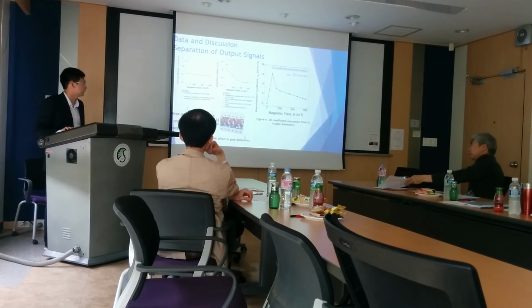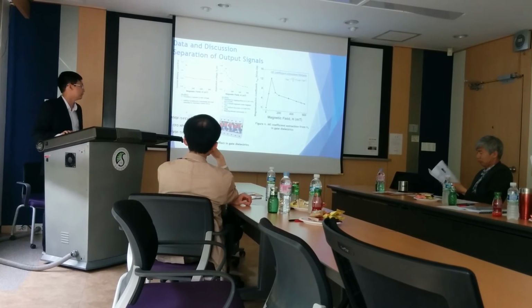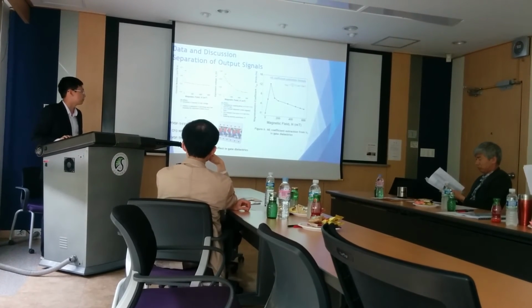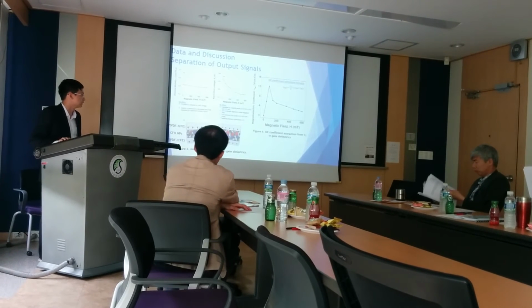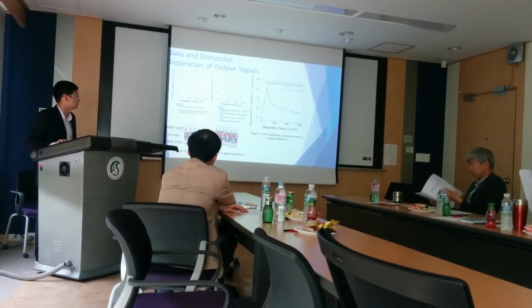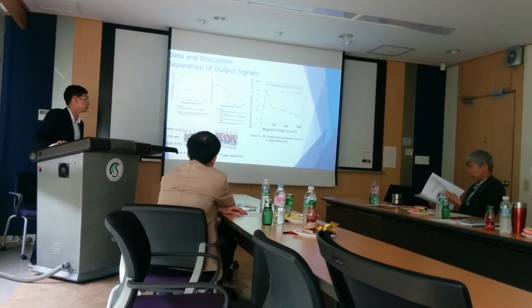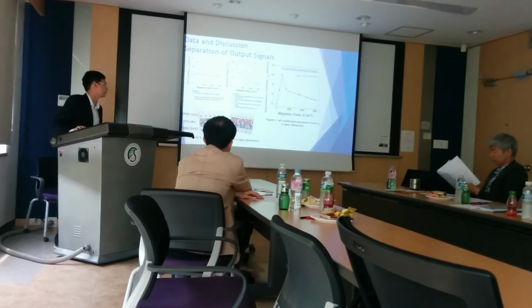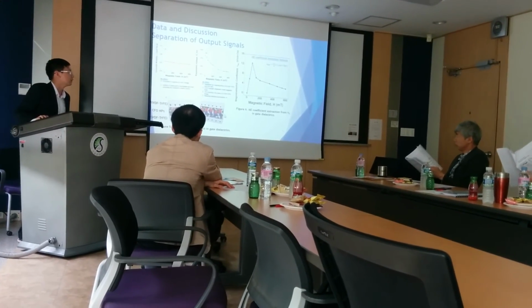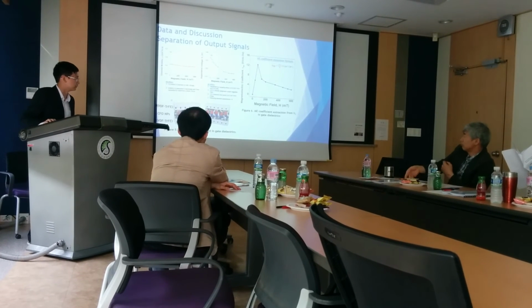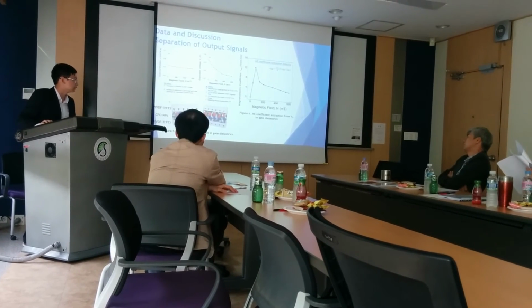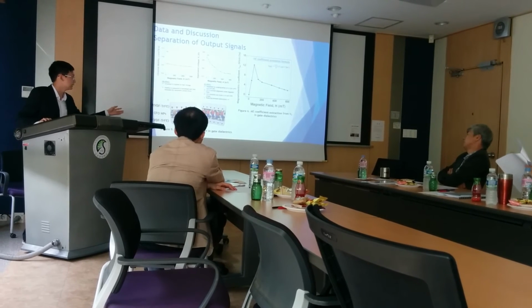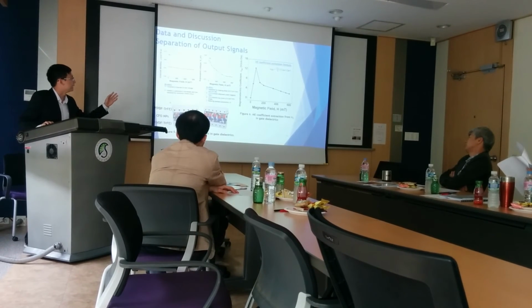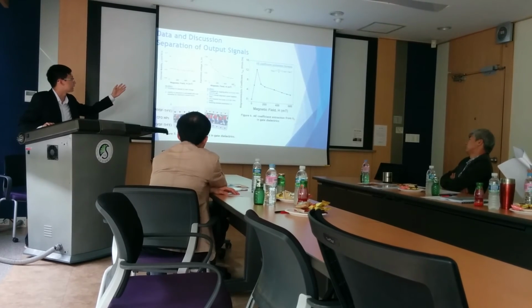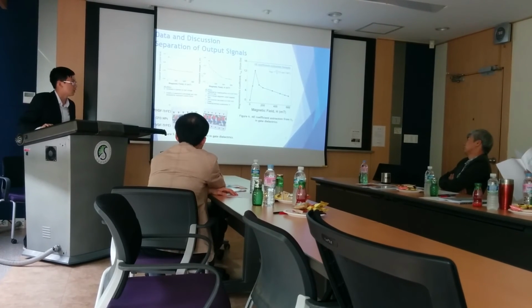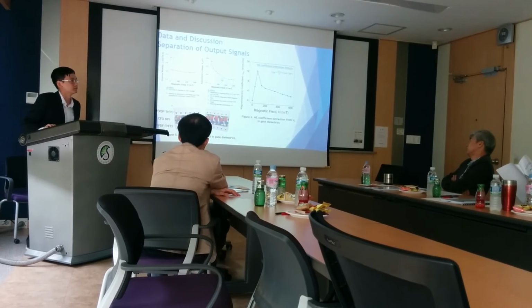As you can see in figure 5c, without the magnetic field, there is a random orientation of the domains of the CFO nanoparticles between the two PVDF-TrFE layers. And when we apply the magnetic field, the domains of the CFO nanoparticles will align with the external magnetic field. As a result, it will decrease the polarization of the PVDF-TrFE. And as you can see in our data, the equivalent voltage D0 of the piezoelectric was reduced.